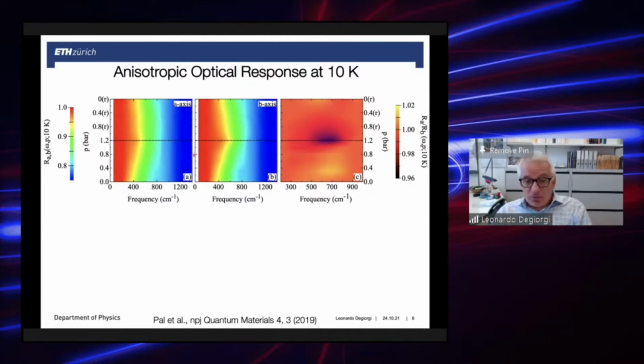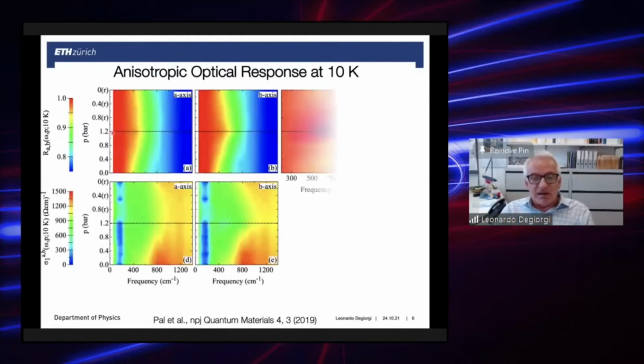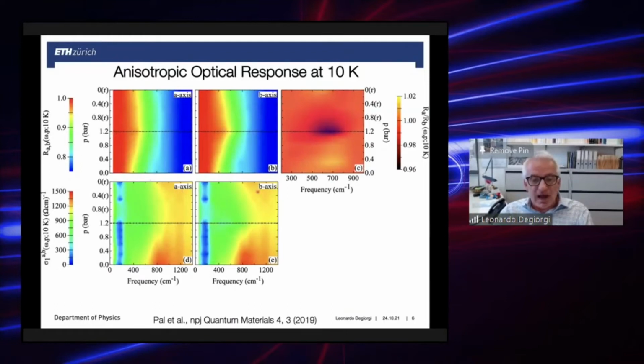Now, we did perform the measurement, obviously, as I said, all the way up to the ultraviolet, so at much larger energy scale, which is the prerequisite in order to perform reliable Kramers-Kronig transformations of the measured reflectivity. And this allows you to have access to all optical functions, like, for instance, the real part of the optical conductivity, which is shown here for both axes in the same spectral range as before as a function of the tuned stress. And here we observe some interesting features, this sharp drop basically to 0 of the real part of the optical conductivity, which later on will be associated with the relevant energy scale, and a finite optical conductivity at the lowest energy spectral range which we can reach with our experiment.